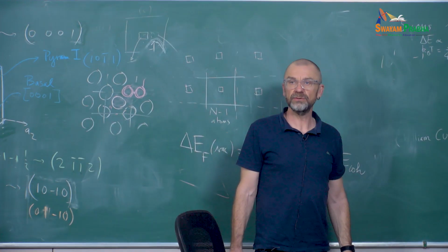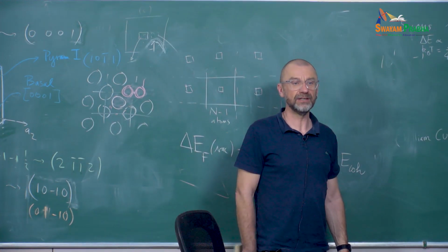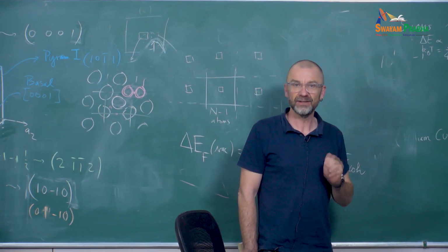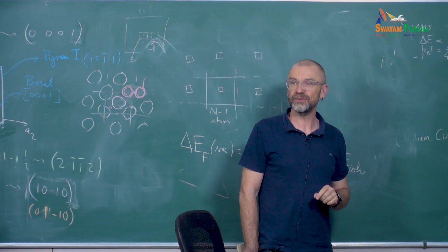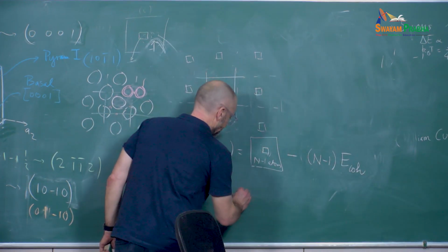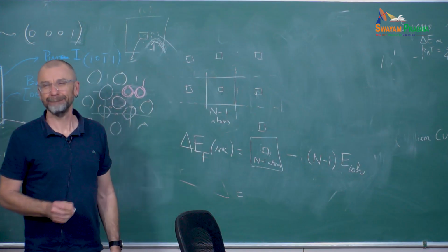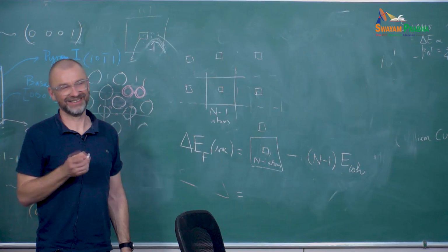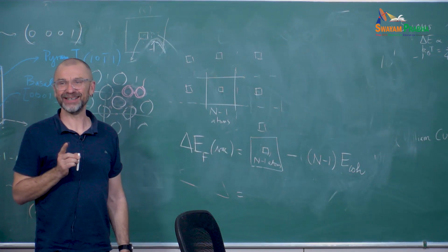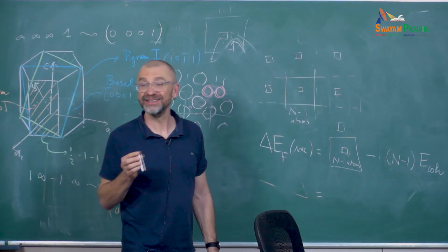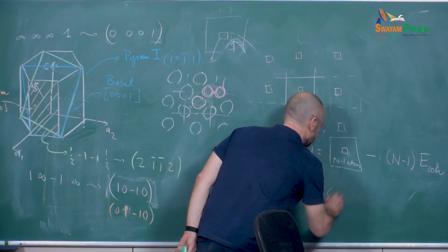So what's the formation energy in aluminum for that potential? It does not mean it's the exact one, but what did you find, those who did the calculation? I know some of you did it because I've seen the results. So how much is the formation energy? 0.68, yes.